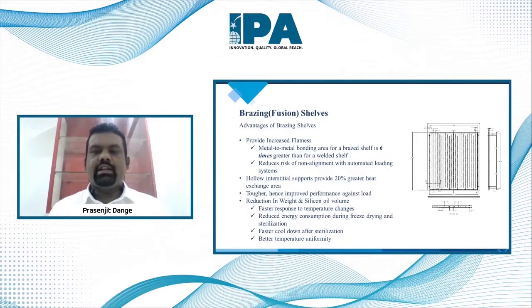lower in width. Earlier, shelves were in the range of around 24, now it has already been changed to 18 for the width of the shelf. Because of that, the silicon oil quantity is also reduced, and then the power requirement for cooling and heating of the silicon also reduces. It also has a faster response to any kind of temperature requirement. It's also faster cooling down after the silicon sterilization cycle, and the uniformity is better.